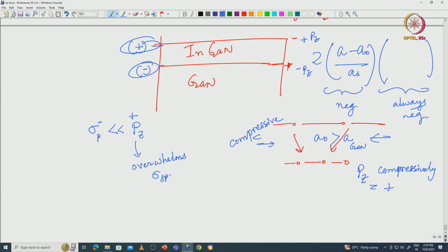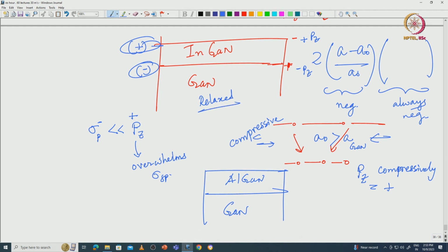Okay. So, in all this discussion, whether it is InGaN on GaN or, say, for instance AlGaN on GaN, when we talk about these different polarizations, spontaneous and piezoelectric, we need to keep in mind that the gallium nitride layer, which is relaxed and therefore has no piezoelectric component, still has a spontaneous polarization component, which is negative at the top and positive at the bottom, correct. In between there is no polarization, because as I told you, when you pile up one unit cell on top of another to form the total crystal, this is negative, this is positive, this is negative, this is positive, they all cancel out. Only what remains is the negative on the top and positive at the bottom; everything else is cancelled out.